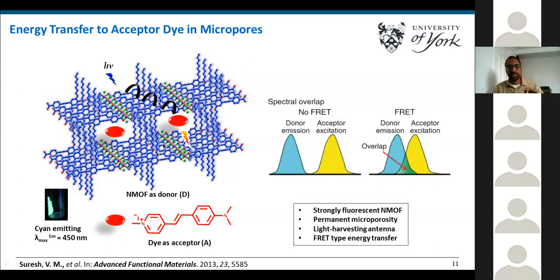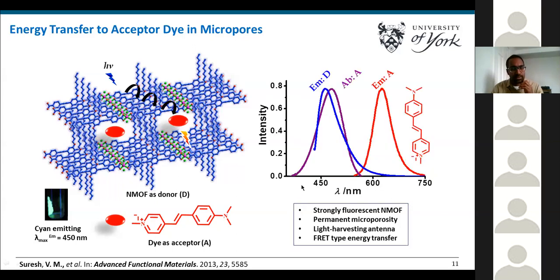So for this transfer to happen, there should be a good spectral overlap between the donor emission and the absorption of the acceptor. When there is no overlap, there will be no energy transfer, so we would not see the emission from the acceptor. The dye we have chosen and the MOF have an excellent spectral overlap. Here you see the emission from the donor, in the blue curve, is completely overlapping with the absorption of the acceptor. So we could definitely see a clear energy transfer from the MOF donor to the acceptor dye.